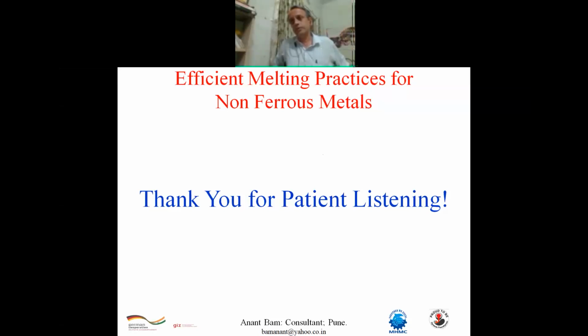Generally, they do it in 2 hours. It depends on the die to die. Sometimes the casting is heavy, then it takes less time. Correct. So see to it that your metal is consumed within 1 hour maximum. So you may have to go for a smaller crucible, or you may have to increase your number of dies. There's no space to increase the number of dies. The furnace is already a small size furnace, so more than 3 people cannot be accommodated.